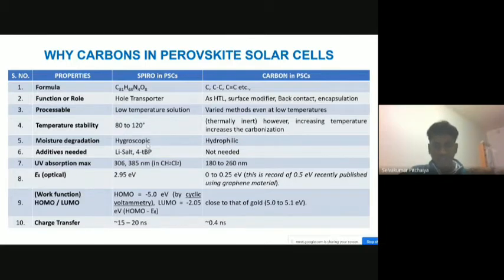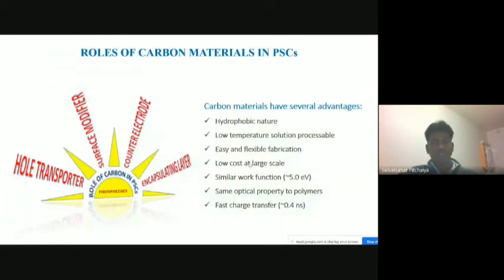It costs about $500 per gram. So it is hugely costly, and in order to replace this material with one having similar properties, we have chosen carbon as our alternative material, and it almost satisfies all the requirements to do the work of Spiro. You can also utilize this carbon layer in various layers of the perovskite structure, and it has outstanding behavior in photovoltaic technology.